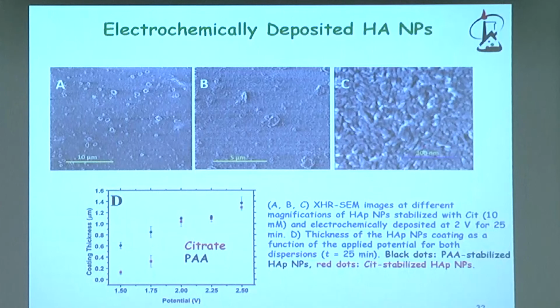And the beauty of this approach, and that's why we call it from nano to nano, is that we start nano in dispersion and we end nano, still nano on the surface. The deposit is still made of the same nanoparticles. And again here, with the potential, you can control the rate of deposition.